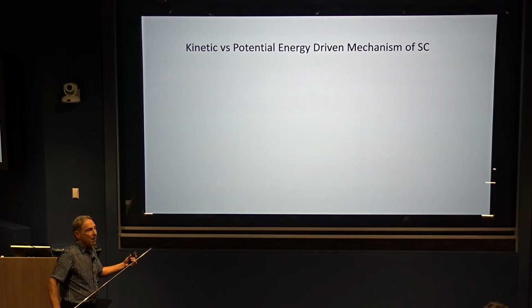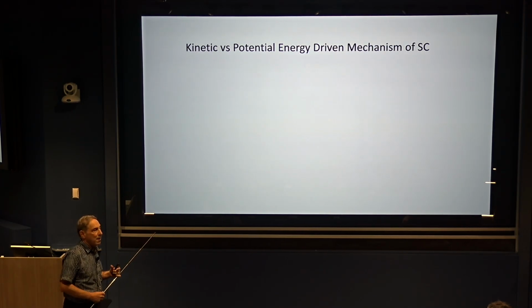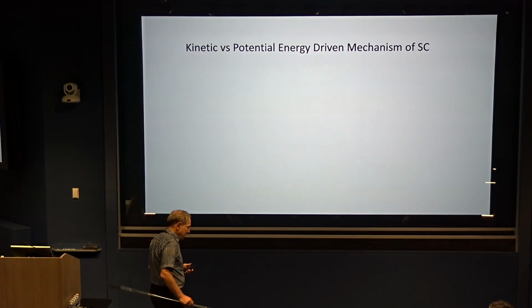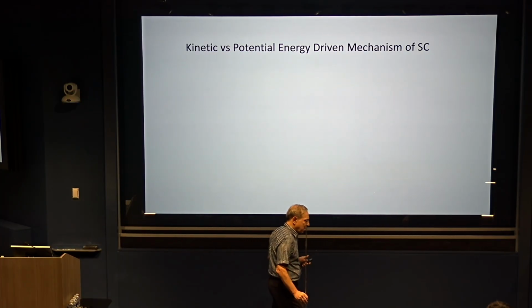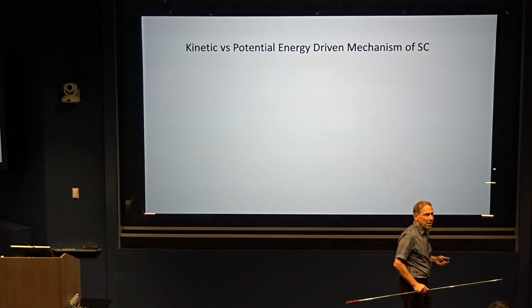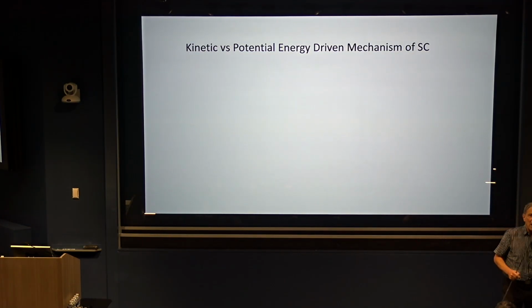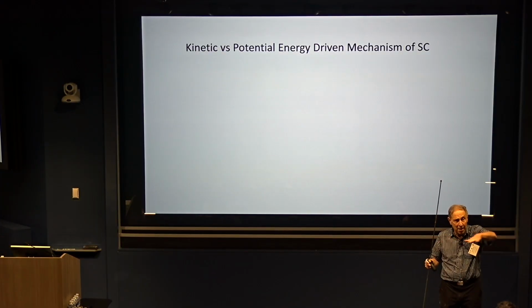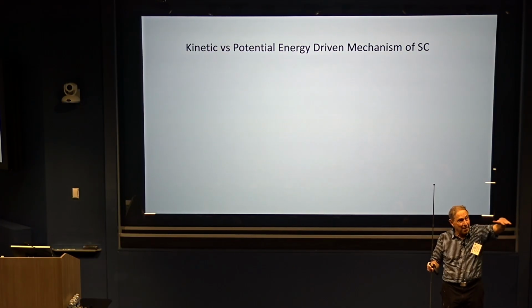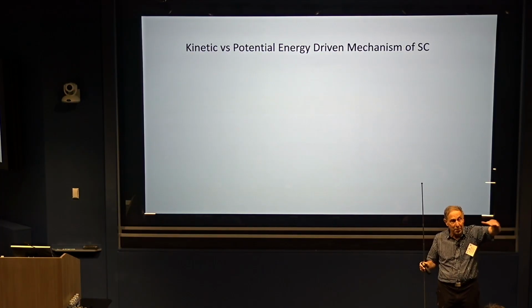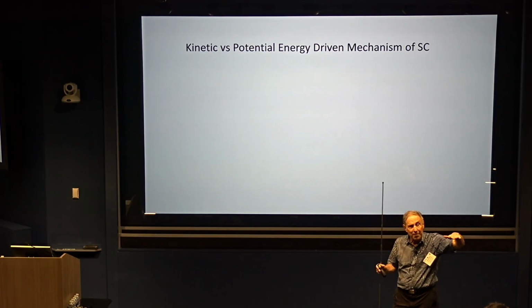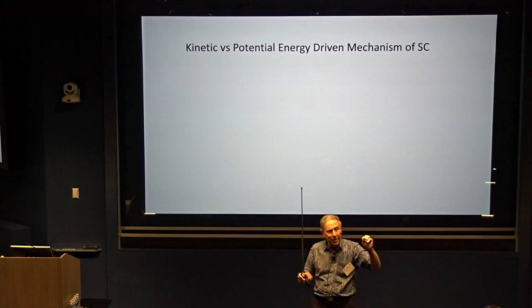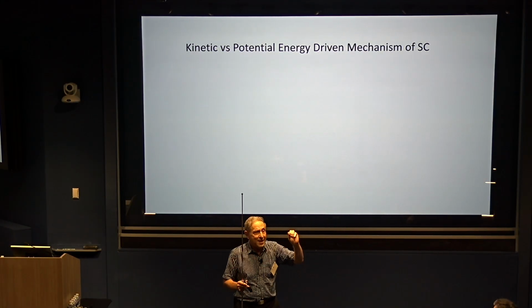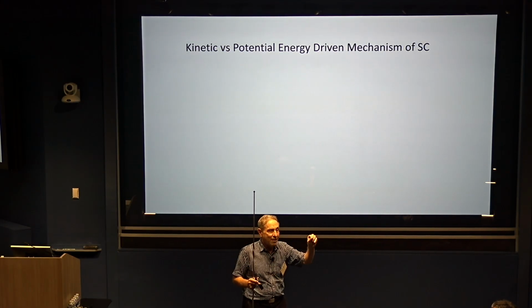Case for Ivan Bozovic or similar people who could really design your original bilayer with different things on different sides. So was that ever attempted? Yeah. So Ivan Bozovic did exactly that. He took an undoped lanthanum cuprate, highly overdoped, 30-some-odd% overdoped lanthanum strontium copper oxide, made a sandwich of them, and found that TC went up to 42 Kelvin.